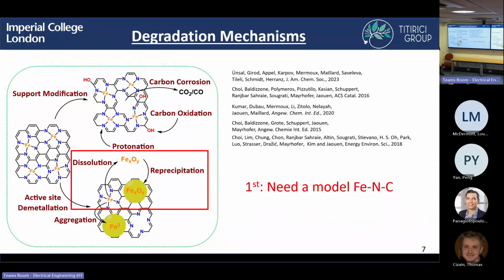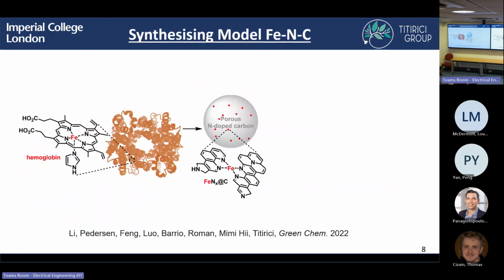But before we did that, we needed to make a model iron, nitrogen, carbon catalyst that purely consists of single atoms of iron in a nitrogen carbon framework. And this is not as simple as it sounds, and I'll go through why that is. So Alan from our group previously showed you can use a bio-derived source such as hemoglobin. You can see here your iron is coordinated already to your 4 nitrogens, and you can use this as a precursor to make these single atom catalysts, as he showed in this paper. The issue with using these bio-derived precursors is you end up, in his case, with a very low iron, nitrogen, carbon density, and so this would limit the performance of the catalyst.